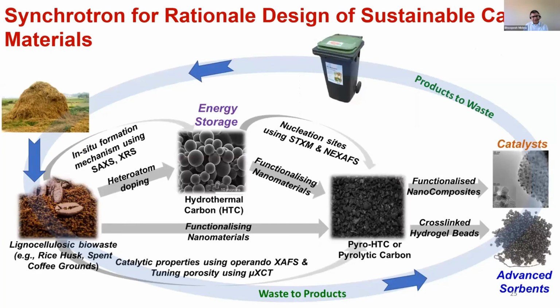And at the end, all I'll say is that what I have demonstrated is that there are many different applications of synchrotron for rational design of sustainable carbon materials. One can start with these lignocellulosic biowaste, such as rice husk or spent coffee beans. One can dope heteroatoms in hydrothermal carbon, which I've shown can be used for oxygen reduction reactions. Further, one can functionalize nanomaterials and form nanocomposites. One example that I skipped today was also the cross-linked hydrogel beads that we have developed.